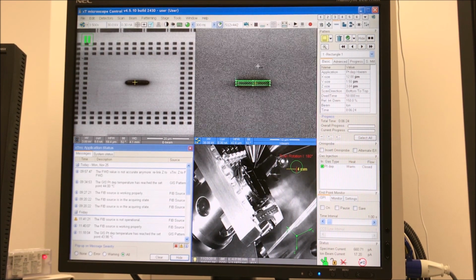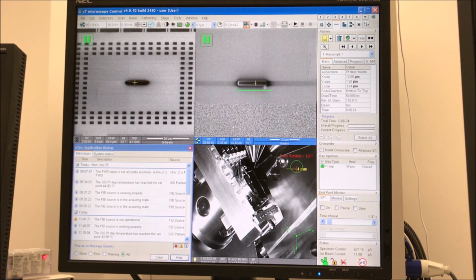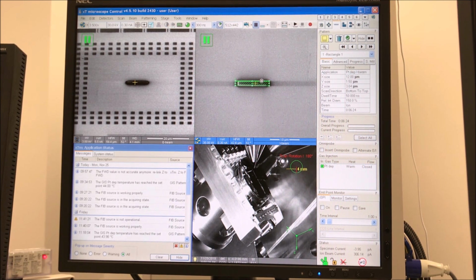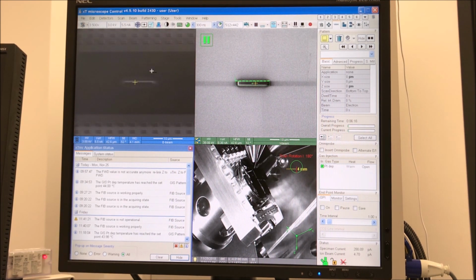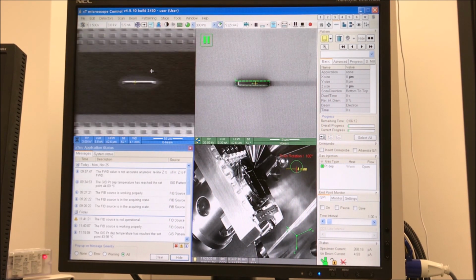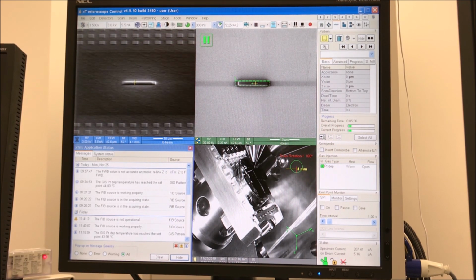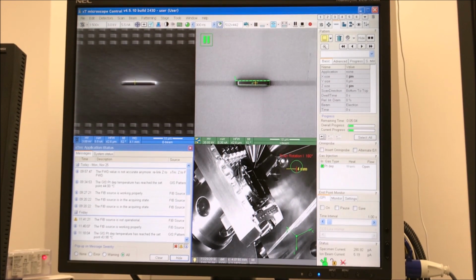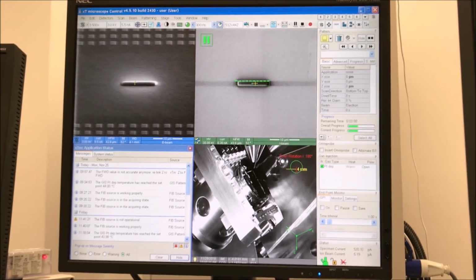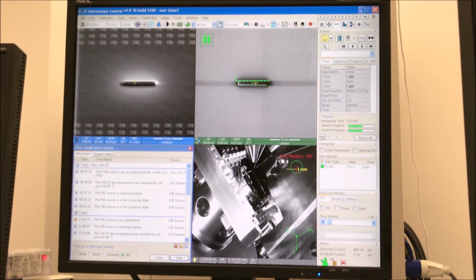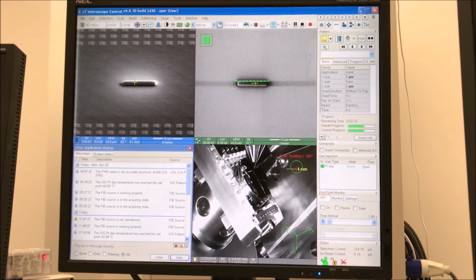So the X and Y dimensions are a little bigger than I used for the E-beam. So the X is now 12 and the Y is 1.5 microns and the Z is 3. And it's important when you're doing ion beam platinum deposition that you have an optimal current density, because otherwise your deposition will be either excessively slow and inefficient, or you won't end up with deposition, you'll end up milling.